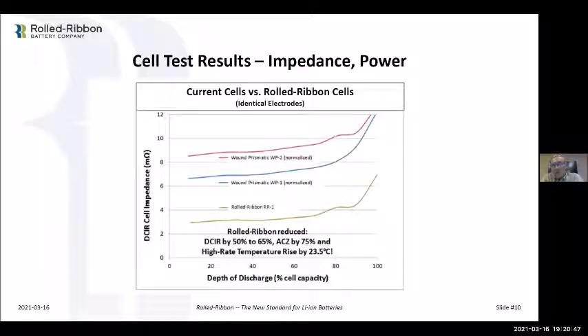But at the end of the day, if you put lithium cobalt oxide, for example, in a roll ribbon cell and abuse it in whatever way you have to in order to trigger thermal runaway, which you can do, you may have to abuse it more than you would with a different cell type, but you can still drive it to the point where it will go into thermal runaway. We'll have thermal runaway too. It's just harder to do, because it's harder to elevate the temperature to the point where it crosses over. I don't know if you know what drives thermal runaway, but basically it has to do with volatility. The principal thing is that the organic solvent they use is very flammable and burns very hot.